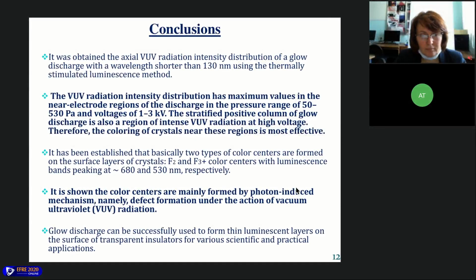So the axial vacuum ultraviolet radiation intensity distribution of the glow discharge was obtained. The vacuum ultraviolet radiation intensity distribution has maximum values in the near electrode region of the discharge in the pressure range of 50 to 530 Pascal and voltage of 1 to 3 kilovolts. The stratified positive column of the glow discharge is also a region of intense vacuum ultraviolet radiation at high voltage. But it has been established that basically two types of color centers are formed on the surface layers of the crystal, F2 and F3+ color centers.